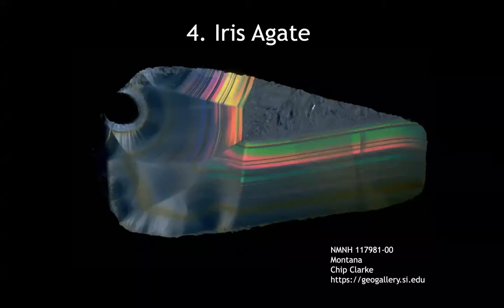But if there are silica-rich solutions that are percolating through those cavities, the silica-rich solutions begin to nucleate quartz crystals in the cavities. And the difference here is that when agates form, there is this very, very fine-grained quartz that gets deposited first, and then there's some kind of a change that results in the deposition of the more coarse-grained kind of prismatic quartz. We call it a quartz druse in geology.